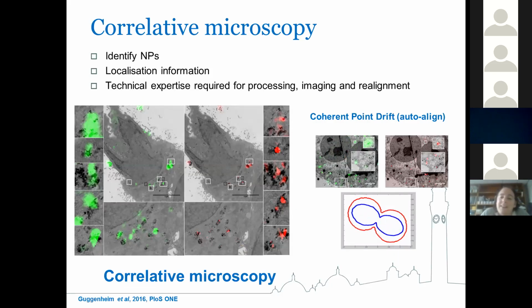So this is just showing one of the things that we had to do, which was to re-stretch out the TEM image to account for the shrinkage that occurred during dehydration. And again, we used an algorithm to allow us to do that. And these are just some examples of the overlay between reflectance imaging and the TEM imaging that allow us to identify nanoparticles, and gives us the ultrastructural information as to where they are. So, for example, that they're in lysosomes or early endosomes or so on.